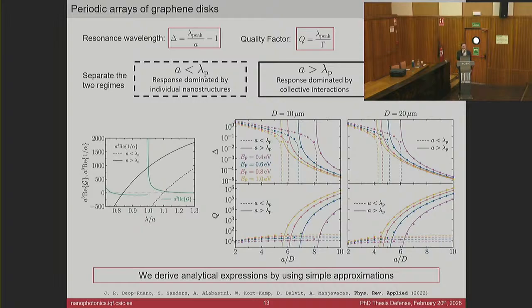This is similar actually to what I have shown for Gaussian beams. That, well, if you are only exciting a few particles, then those few particles maybe cannot sustain the resonance. In the same way, you need an array that is large enough. Then it is not only the size, but also you have to have an array that is perfectly ordered. And any deviation from this perfectly ordered, whether it is because there is some error in the distance between the particles, or because actually they are not exactly equal particles, is also going to affect.